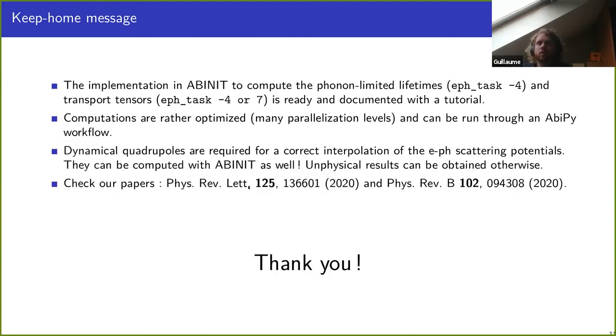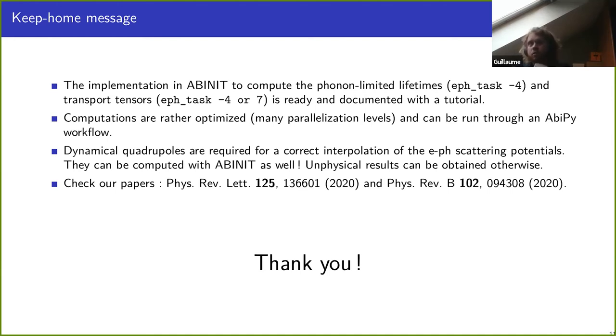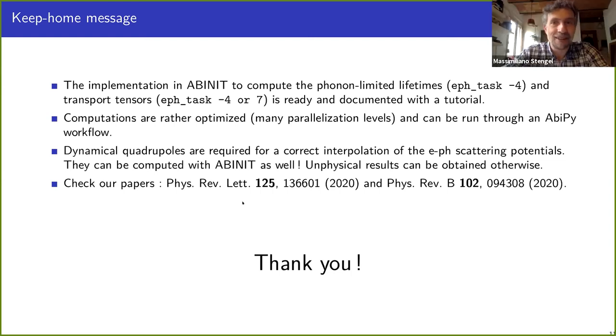We have also created a workflow within AbiPy to compute the mobility in a more automatic way. The take-home messages are: first, ABINIT offers an efficient and well-documented implementation for computing phonon-limited mobility and lifetimes, with many parallelization levels and Python tools to automate input creation and output analysis. Second, dynamical quadrupoles are very important for many semiconductors and can be computed from first principles with ABINIT, giving us everything needed to accurately compute mobility.